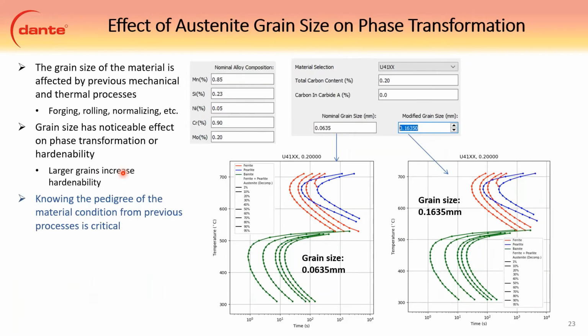We can also consider the effect of austenite grain size. This grain size is in millimeters, so we're going from 63 microns to 163 microns. Again, you can see the shift to the right. So larger grains make it more hardenable.